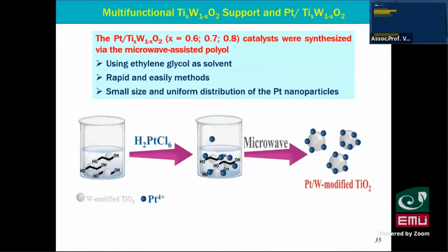The synthesis is not simple either. We use 2 steps. The first step we use hydrothermal synthesis. The second step we use microwave, which uses polyol for reduction.